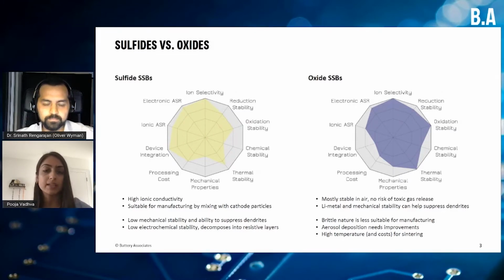The oxides, on the other hand, don't have this sensitivity to moisture, so that's very nice. And they have a high electrochemical stability window with lithium metal. The opposite side for oxides is how you incorporate them into cathode materials. Because they have such a high Young's modulus, you can't just mix them with cathode material. They also require sintering at very high temperatures. So if you mix it with the cathode material and use high temperature to press the materials together, you'll get a decomposition product. So usually you use some kind of wettability or coating layer at the oxide and cathode interface. But again, that's a lot of manufacturing steps.